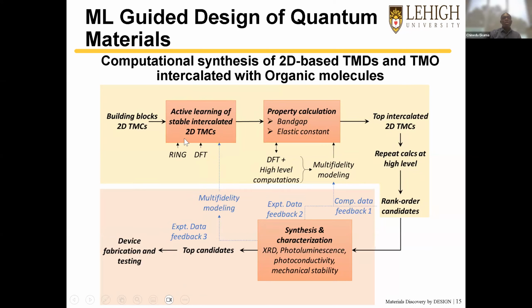At the active learning level, we are using transfer learning, coupled with multi-fidelity, which is a kind of bootstrap-like approach that we do exploration and exploitation. I'm going to share with you how bootstrapping is done. And there's kind of experimental feedback with some of our experimental collaborators, and we can learn some information from what they told us, and we feed it back and keep iterating the process until we get some top candidates. These top candidates, based on our design, we say top 50, we'll do some further high-level calculations using something like density functional perturbation theory for the phonon spectra and